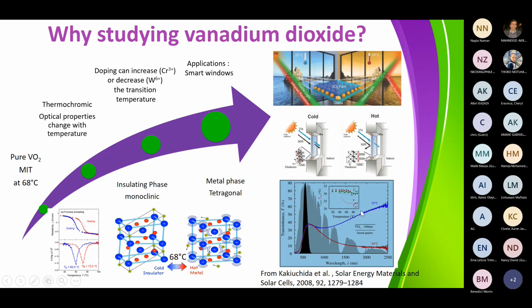My pointer here, you see if you are at 20 degrees Celsius, you have a transmission of about 60% in the infrared region at 2000 nanometer, while if you are at 90 degrees Celsius, for instance, you can see that the transmittance is very low, about 10%. So you kill the infrared radiation in the metallic state, while you let the infrared radiation go through the window if you are in the insulating phase.